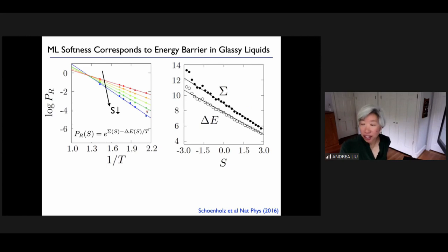The real benefit to introducing this variable softness, the structural variable, is that when you use the same weights at multiple temperatures, and you look at the probability that a particle will rearrange as a function of temperature, so log of the probability versus 1 over temperature, for particles of different softness, so each color here is a different softness, what you find is that the behavior is Arrhenius. Okay? In other words, for particles of given softness, the probability of rearranging has this form, and there is a well-defined energy barrier for each softness for the particle to rearrange.